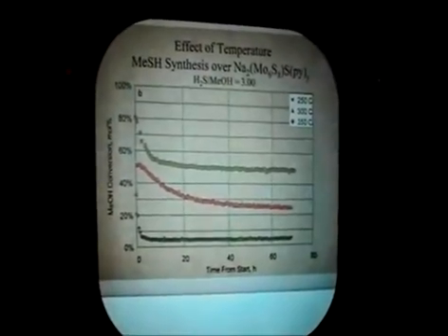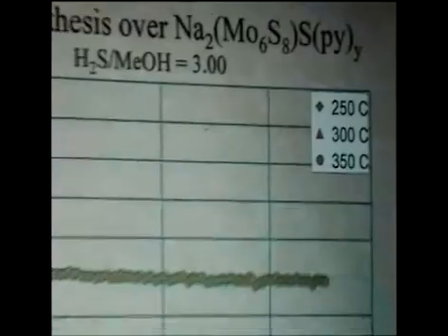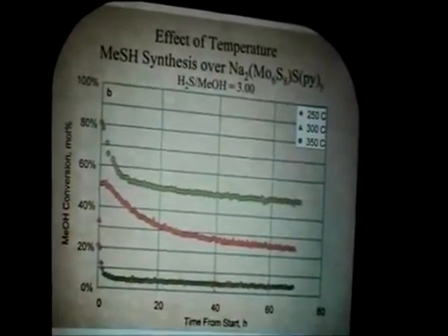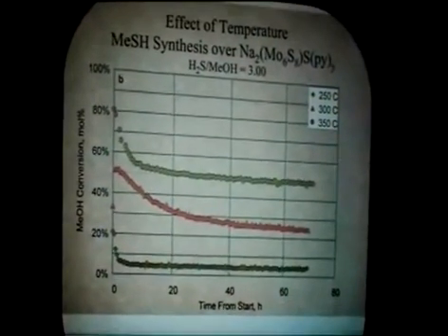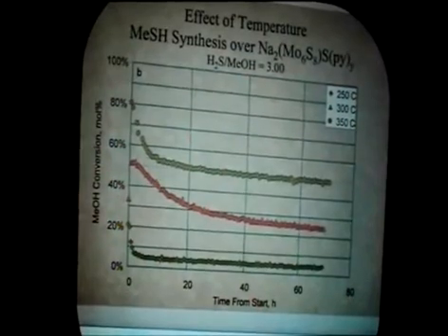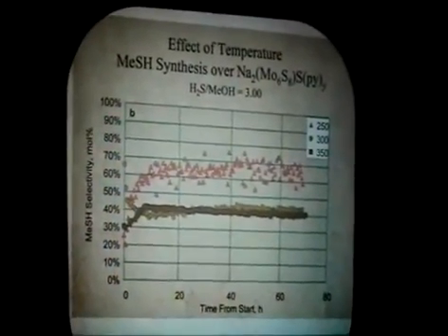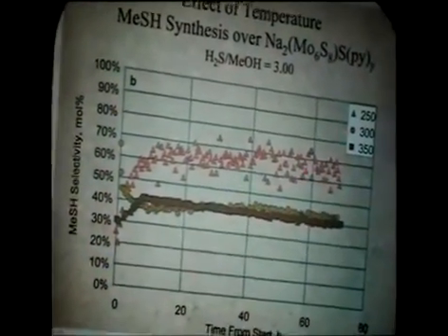In comparison, for this ligated sodium material that showed some degradation to MoS2, the same experiment was carried out. Even though this material initially had pretty close to the same surface area, we could never get as high conversions with the sodium material. And the selectivities here are lower also. What's interesting here is that selectivity didn't decrease anymore after 300 degrees C in this reaction.